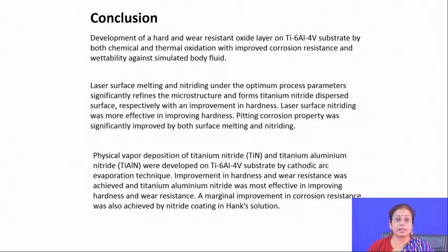So, it can be concluded that nitride and oxide layers on the surface of metallic materials may be developed by a chemical oxidation route, by thermal oxidation routes, or by a typical laser processing route, and this is a very applicable treatment for improving the corrosion resistance as well as wear resistance of the surface. Laser surface nitriding is another way of converting the surface of titanium as well as steel to its nitrides, and as it is carried out in the molten state, you will find that there is a quite homogeneous surface and the interface is also quite strong, with no problem at the interface.